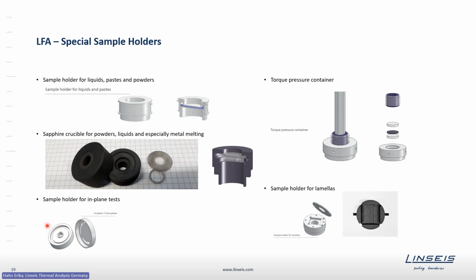For foil samples or in-plane tests of thin materials, one can use this adapter. We also have some containers for pressure-dependent analysis. Typically, the laser flash method is a contactless method where we don't apply any pressure to the sample. But with this sample holder, one has the possibility, using a torque wrench, to define the pressure on the sample. For a really special application, the measurement of lamellas, we have also designed a sample holder. This sample holder is, for example, also used for in-plane measurements. First one measures the bulk material with the classical sample holders, then cuts some slices out of the material, turns them by 90 degrees and places them into the sample holder for lamellas.